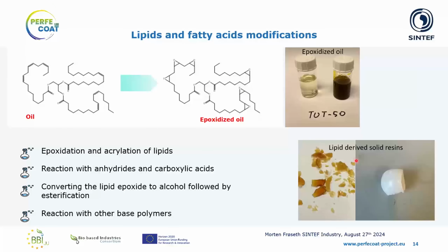At the end, we have the fatty acids, lipids, oils. Usually they are well known in the paint industry, but then usually as an alkyd, where you have functionalized polyester with a fatty acid chain. In this project, we have been thinking a bit differently. We have tried to change the reactivity of the saturation of the lipids. For example, by introducing epoxide, which can be used further to introduce, for example, acrylic acids that can be UV cured.